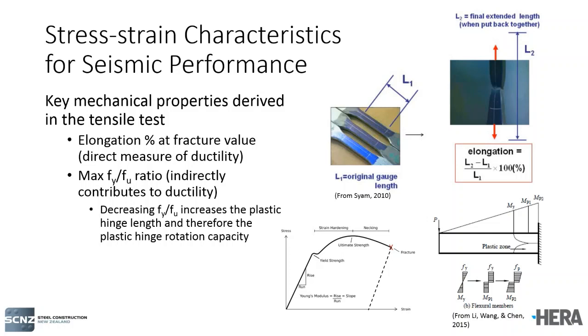So what are some of the stress strain characteristics of steels that contribute to good seismic performance? One of the key requirements for steel, and a direct measure of the ductility of structural steel, is the elongation percentage at fracture value, and this is derived from a tensile test. We see here some test samples that have been taken from the steel. They've been machined into essentially what looks like a dog bone shape. The idea of machining the sample down is that we force the yielding into this necked down region. There are some gauge marks that are placed on this yielding region. We measure them prior to the test.